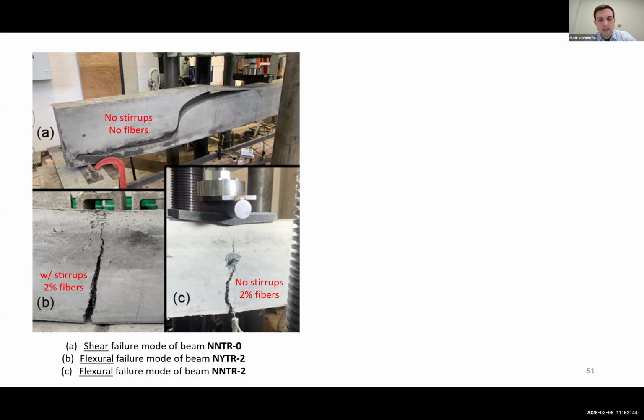And then the C is when we removed the stirrups, we actually found that for this mix, if we didn't use the stirrups, the 2% fiber dosage was enough to handle the resistance for that internal diagonal tension that caused the shear failure in the first test. So it's really showing that the shear reinforcement wasn't needed from a behavior perspective. You may still add them for structural safety and reliability, but from a pure behavior perspective, it wasn't needed in this case.